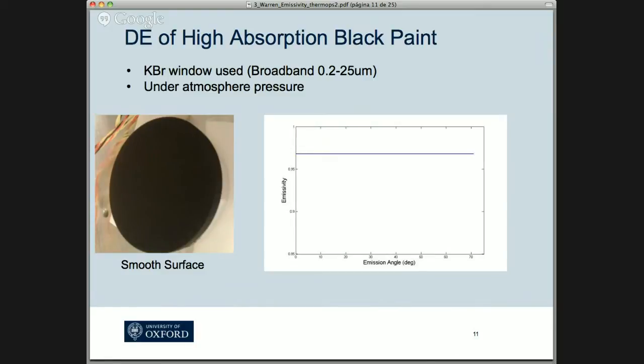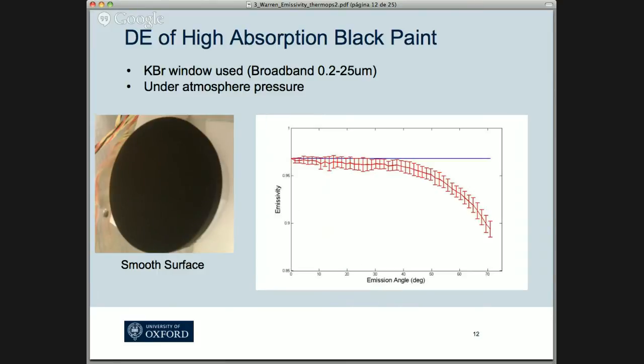I naively sort of expected the response of this direction of emissivity of this sample to look like a straight line, like an isotropic sample. So same emissivity no matter what viewing angle you viewed it at. Of course, when I measured it, this is what I measured. Definitely not isotropic, particularly at 45 degrees and above.